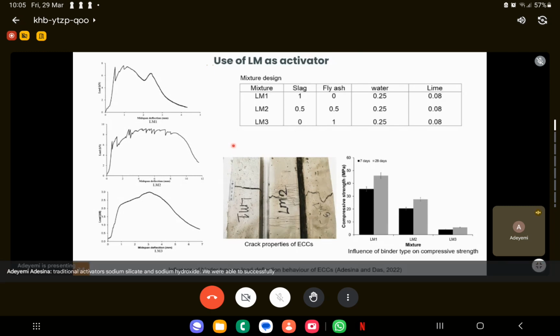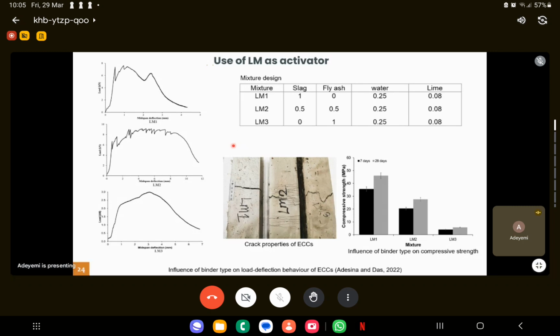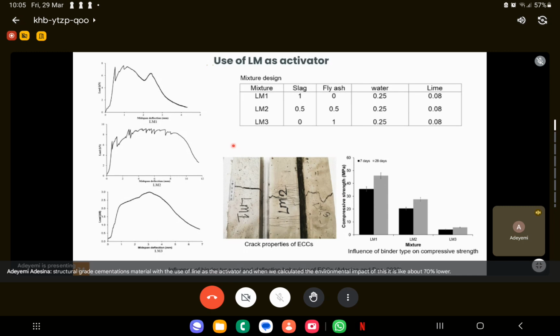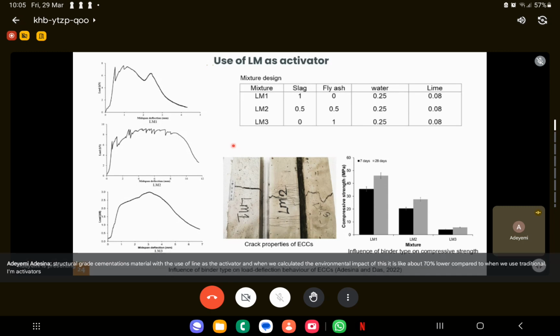And when we calculated the environmental impact of this, it is about 70% lower compared to when we use traditional activators, and about 90% lower compared to when we use cement. But we can see in this case, because what we're looking for is these multiple cracking, we found that the combination of slag and fly ash gave us the best results.